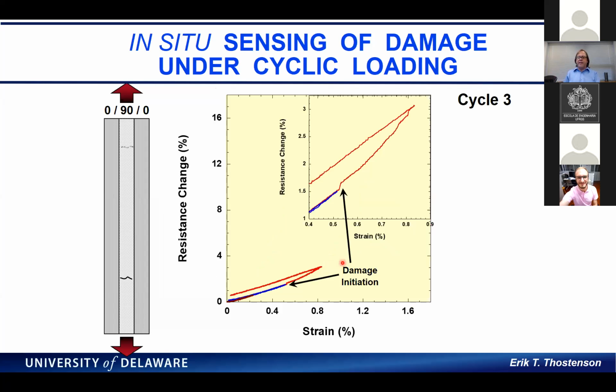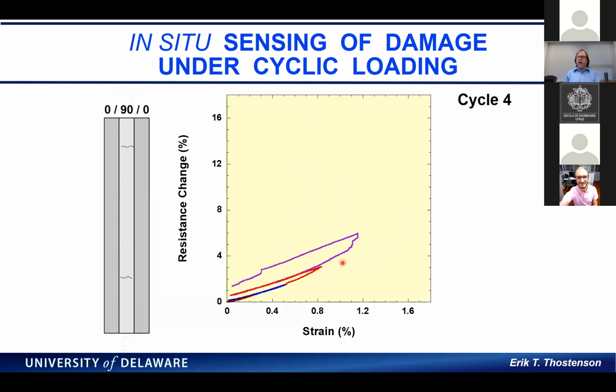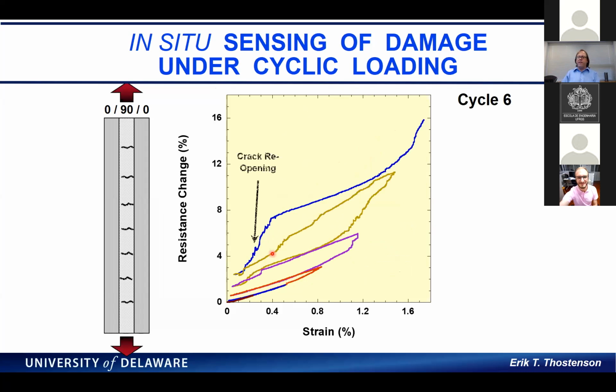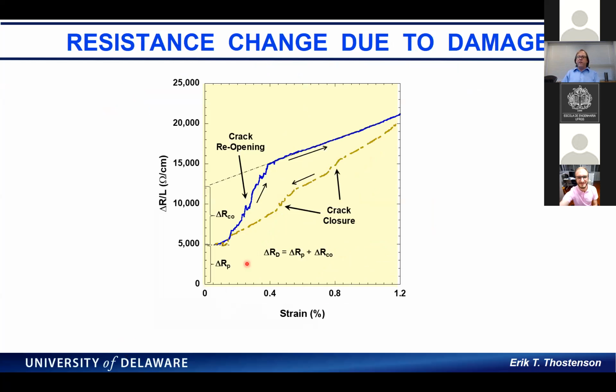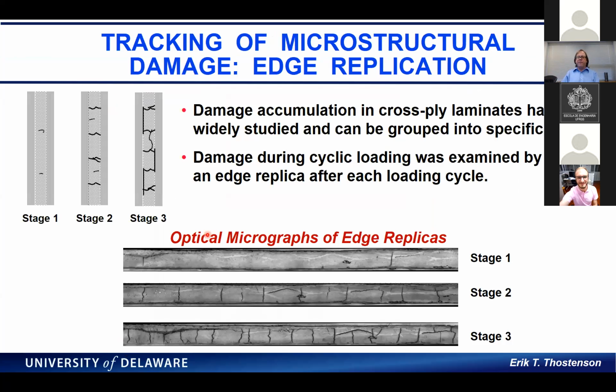And this is just that same data plotted in a different way that shows you that damage accumulation, the crack closure, and the crack reopening. We did some very careful measurements. We call this the damage resistance because there's some permanent resistance change and also change due to the crack reopening.